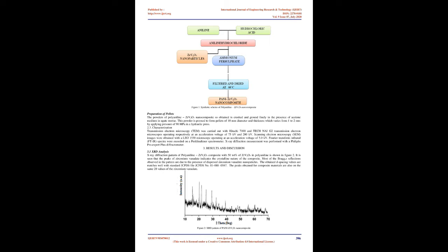0.1 mole of aniline was dissolved in 1 M HCl to form aniline hydrochloride. Zirconium vanadate is added at 50 weight percentage of aniline hydrochloride solution with vigorous stirring in order to keep the zirconium vanadate suspended in the solution. To this reaction mixture, 0.1 M ammonium persulfate, (NH4)2S2O8, which acts as the oxidant, was added slowly with continuous stirring for 4-6 hours at 0-5 °C.